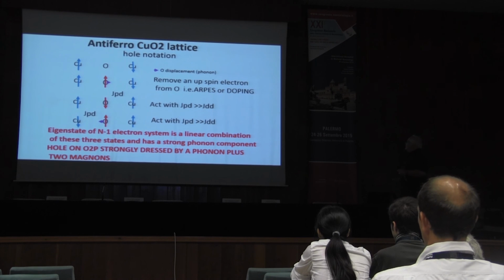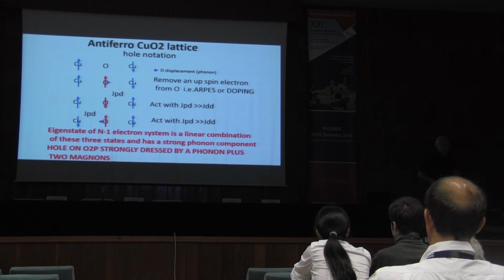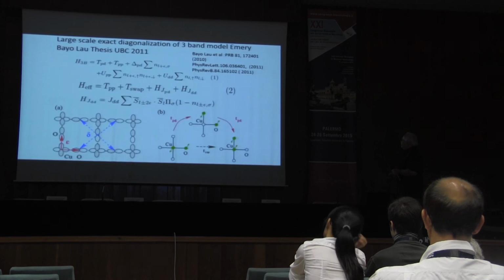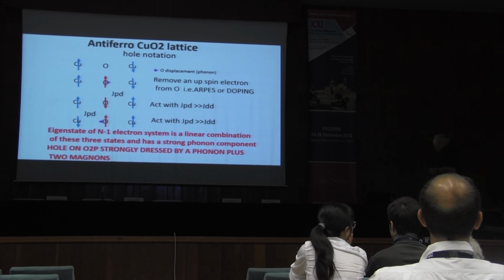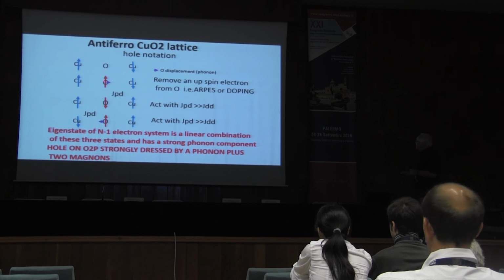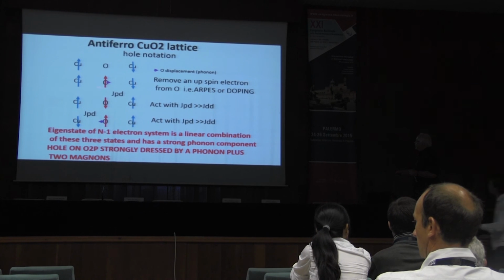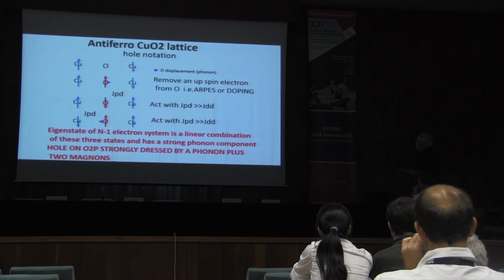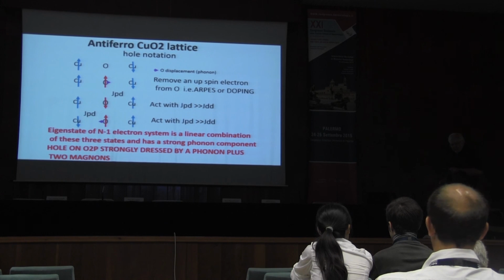Now, what is that state? Well, it's a very interesting state. Remember, I started out with 2 copper spins that are strongly antiferromagnetically coupled. I put in an oxygen hole. Let's say it's spin up. But this spin up hole, this oxygen, you would think is in inversion symmetry, right? But it's not, because the spin has a particular choice. As soon as you put a spin there, it's no longer in inversion symmetry. And actually, it would love to be a little bit closer to this copper, because then it could even have a larger exchange interaction here, and it wants to get away from that repulsive, because this is a very strong antiferromagnetic coupling, much stronger than that. Okay?